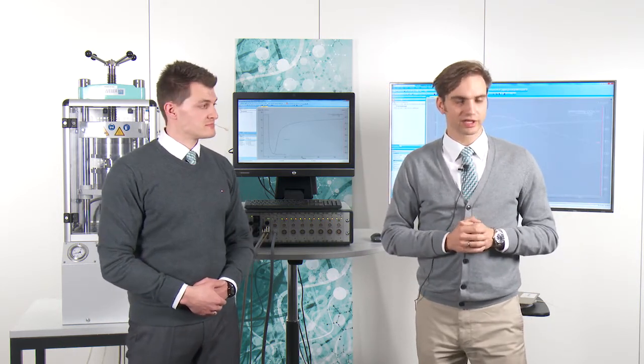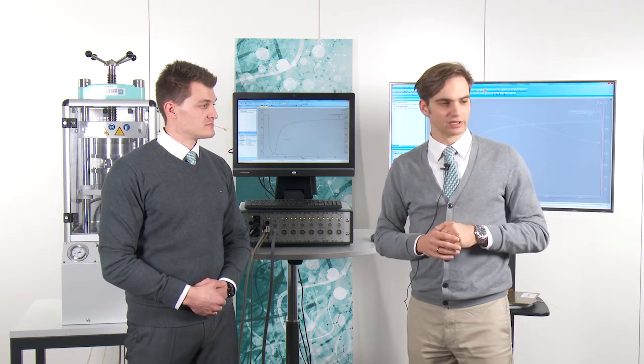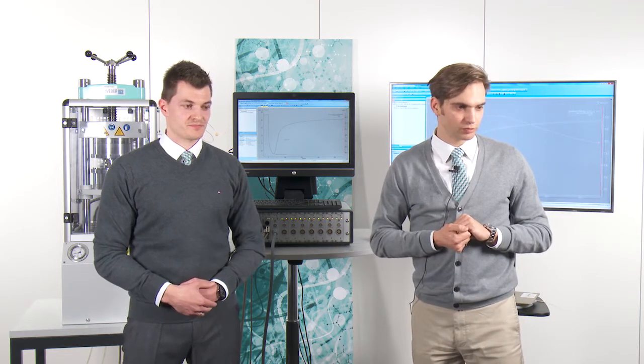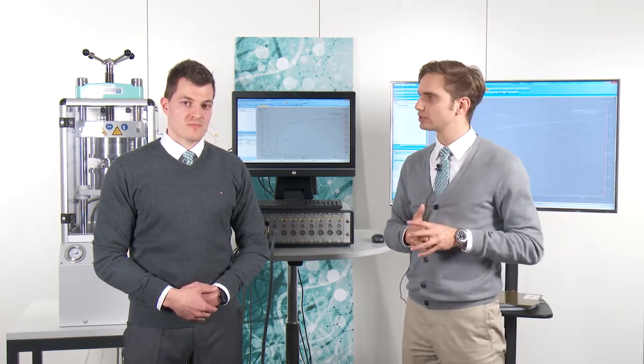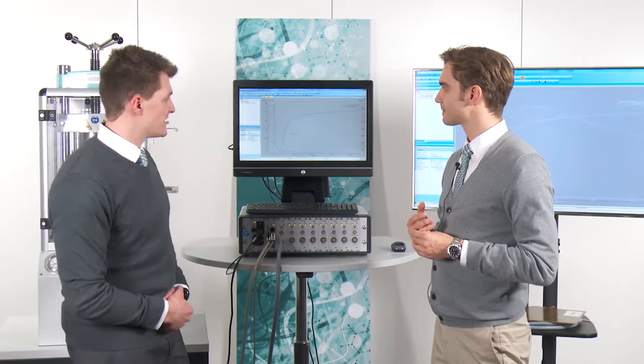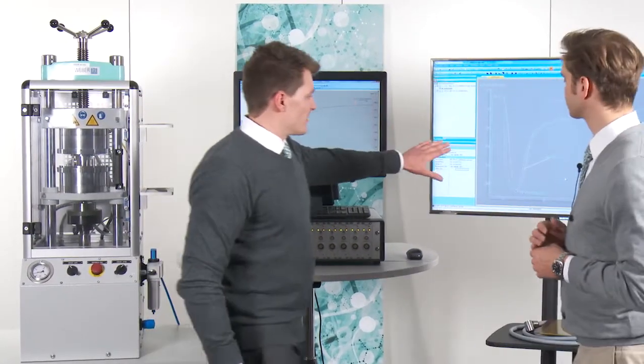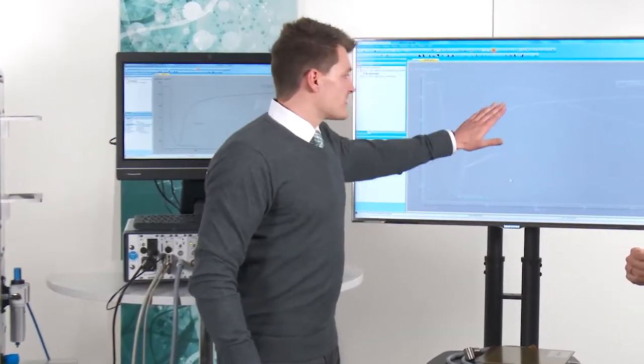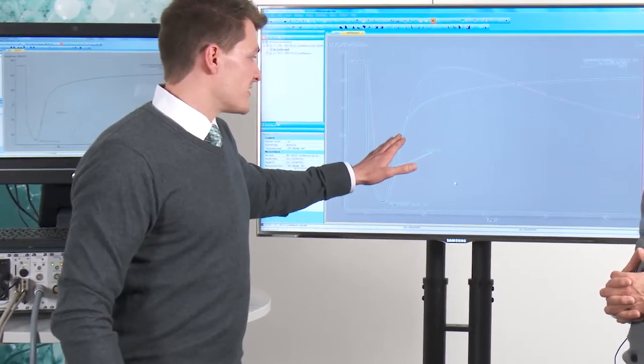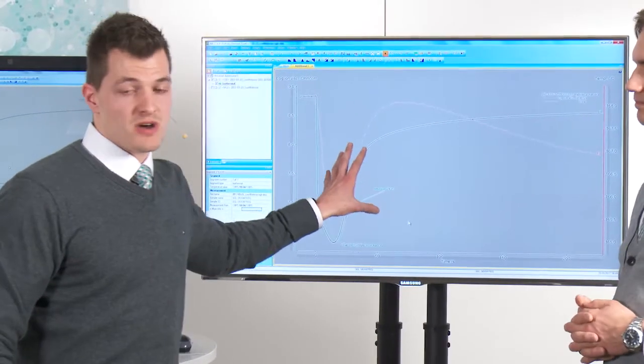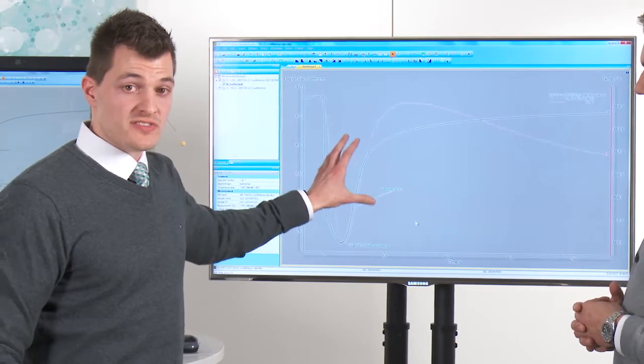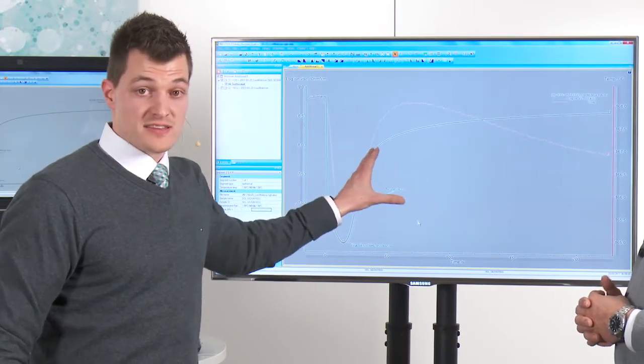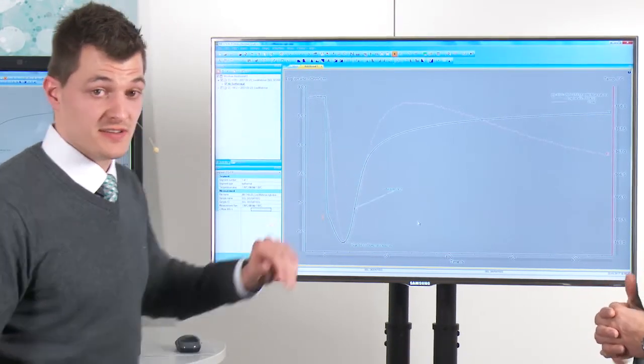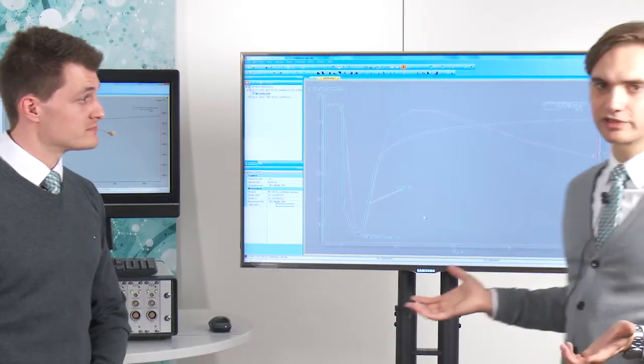Some more questions that we got from the audience. First one would be how to measure the curing rate of the curve. Yeah, as you could see, here's a question from Finland. If you have a look at the increase of the ion viscosity, the slope of this ion viscosity gives you direct information about the rate of cure, so the cure speed at this point you're interested in. Okay, so if you look at the first derivative, maybe for example, this is your curing rate.